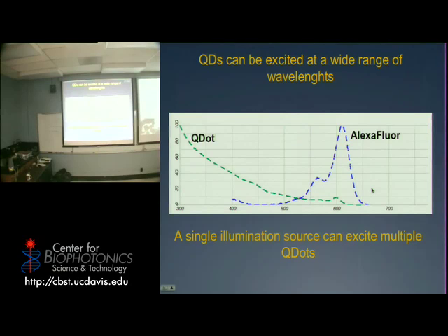Exactly. And as you can see, especially here, which is the range where you will want to pump light in, the absorption is actually minimum. If you want to heat them up to some extent, you have to excite here, but this is closer to the UV, so there's not a lot of penetration. So in actuality, they do heat up to some extent, but not nearly as much as gold does. So quantum dots are not helping for photothermal therapy. Gold is good. Quantum dots are good for other things. Think more imaging.